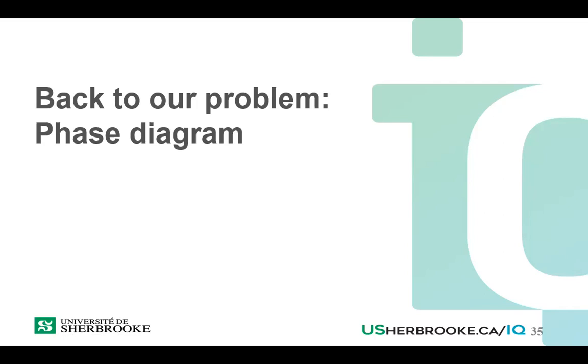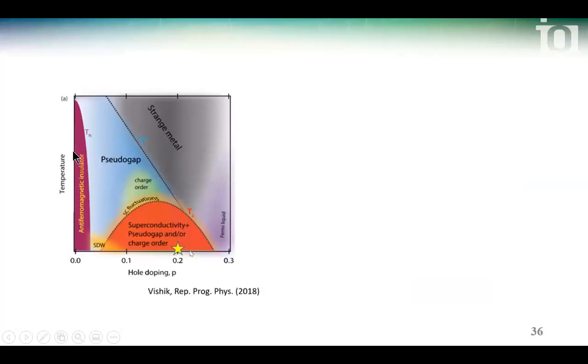Okay, the phase diagram. I've already explained the antiferromagnetism when I explained to you the effect of J. Yes. So this method is mainly for two-dimensional strongly correlated systems. You can do it in any dimension you want, even three dimensions. Yes, and it works best in infinite dimension where it's exact. But the cluster sizes are bigger in three dimensions, so it's harder. Well, it's always a problem of computer power, in the sense that even these small clusters are in an infinite bath. So it's still difficult to solve. And this bath is dynamical. I mean, it depends on frequency. That's what's important. This G0 is a function that depends on frequencies. You have a mean field that depends on frequencies.